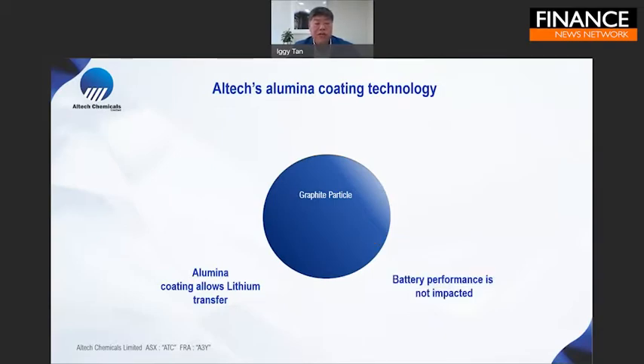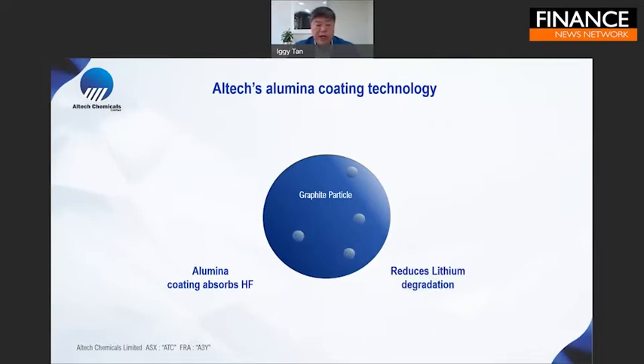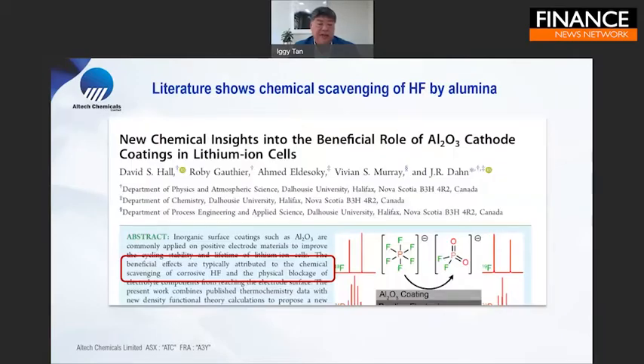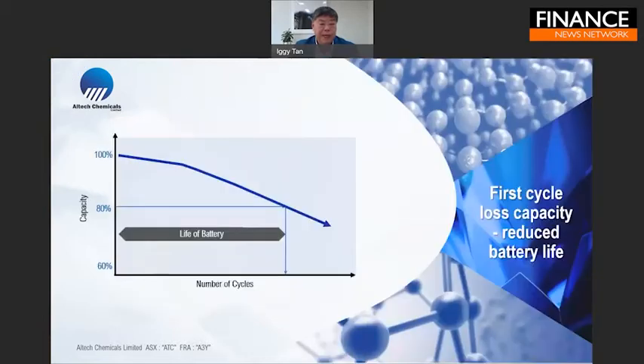And what's the more interesting thing is that there's a lot of research that shows that alumina absorbs this corrosive hydrofluoric material that I mentioned before, and it turns it into an inert material. And typical of some of this literature, this is some people that did the work, and they say that the alumina coating scavenges the corrosive hydrofluoric ions. Now, if you look at the coated versus uncoated, that's what we're aiming for.